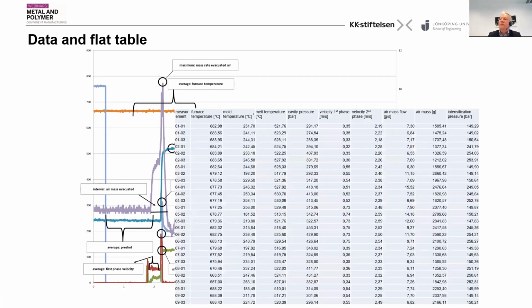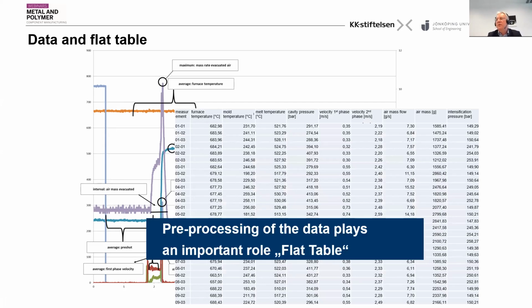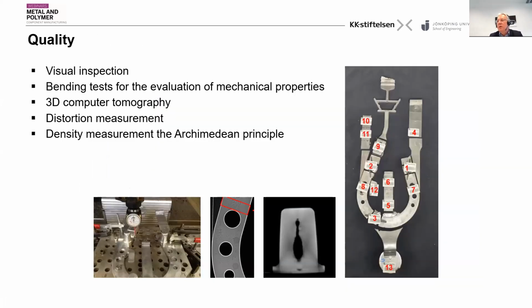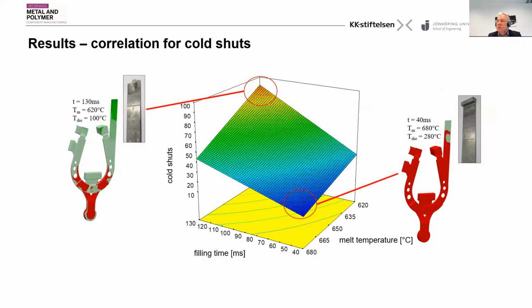Until now, you have to take all this data, extract maximum data or the points of the curves you think are important, and produce a flat table out of it. And then with this flat table you can go into your DOE and try to get information which is connected to quality. For quality, we did visual inspection, bending tests, computer tomography, which is very slow, distortion measurement, and other stuff like this. And you get a big correlation matrix between the process parameters, sensor data, and quality. You can see in red here that this temperature gives an idea of the density of the part or whatever, but it's not so easy to do this.